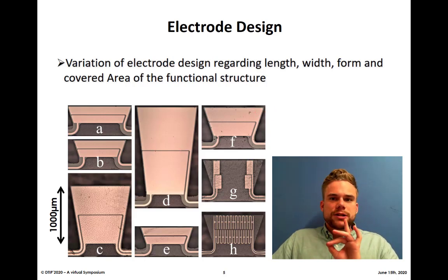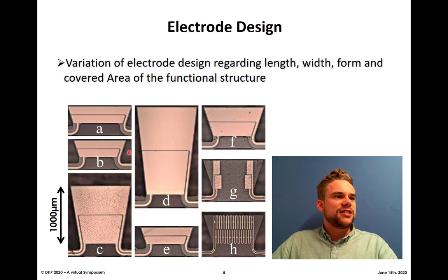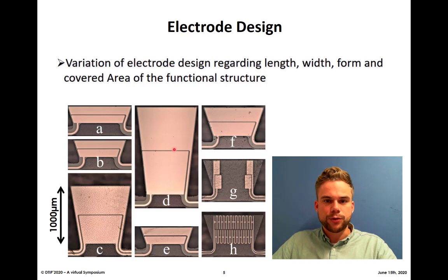And basically I will just go briefly through the different electrode designs here. So this scale here is the real scale for every flapper. The length of flapper C, for instance, is 1000 micrometers, which is of course 1 millimeter. So that is the dimension we're talking about here. And we just go briefly through that. The difference between A and B is that A is just wider than B, everything else is kept the same. C is of course longer, but still smaller than D, and F is smaller than C. So we started at F, double the length for C, or triple the length for D. The rest is kept the same.